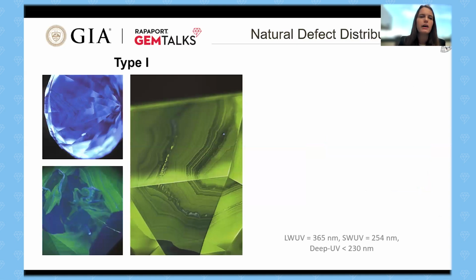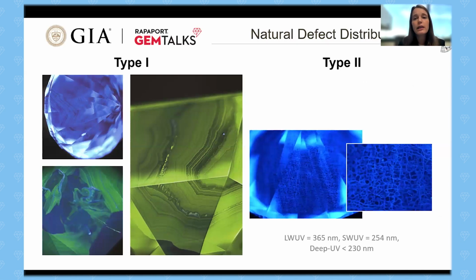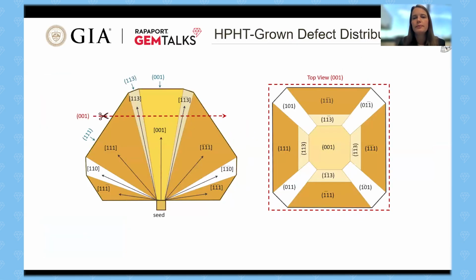Natural diamond patterns depend on the types of impurities that are present. So whether it's a type 1 diamond with plenty of nitrogen, or even a high purity type 2 diamond, you will have different characteristic natural patterns. In fact, for the type 2 diamonds, which is the diamond type that we're most interested in when it comes to distinguishing from laboratory-grown diamonds, you would oftentimes see this sort of mosaic polygonized dislocation network. So it almost looks like cotton wool going through the stone. And this has to do with the way that the diamond has been formed.